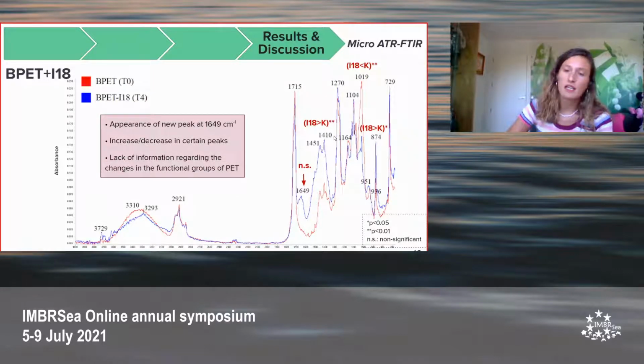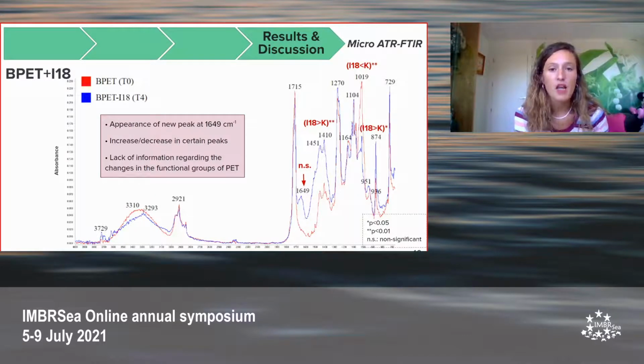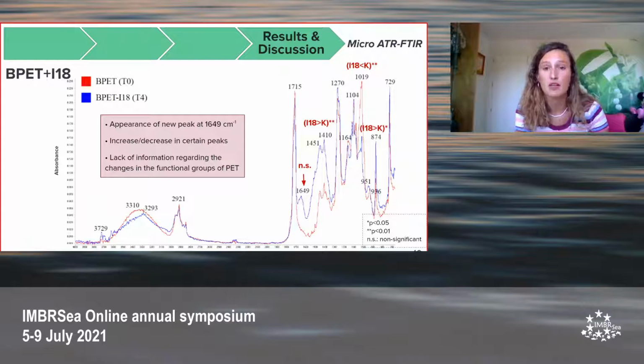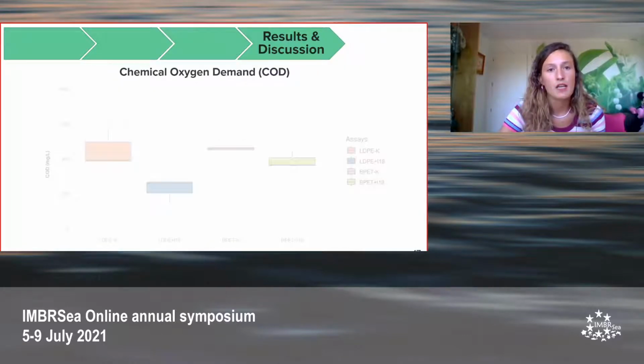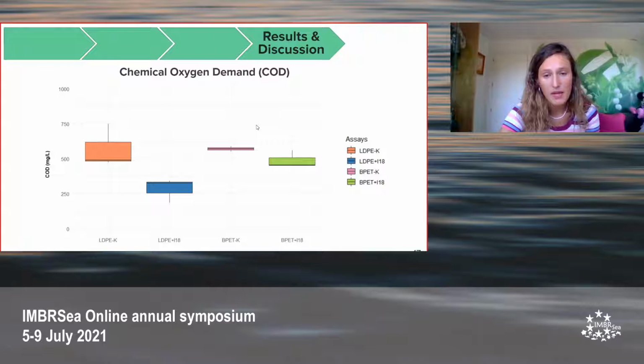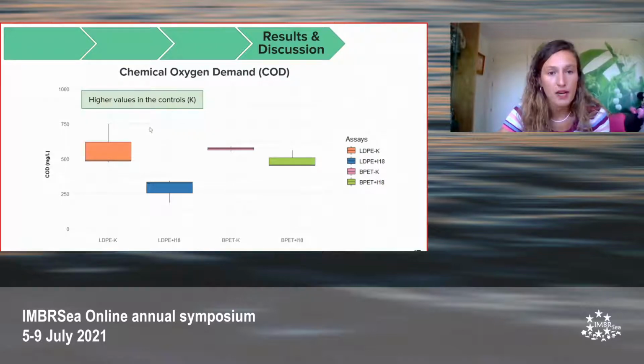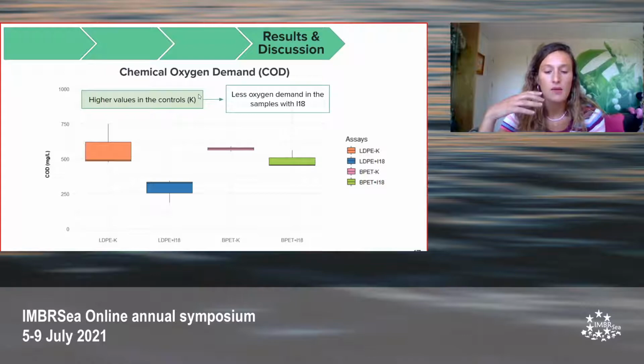These shifts could indicate that the polymer is being degraded. However, there is a lack of information regarding the changes in the functional groups of this polymer. But these results could, in this sense, pave the way for further interpretation of the biodegradation of polyethylene terephthalate. In the case of the results of the chemical oxygen demand, as we were expecting, we obtained higher values in the controls compared to the ones with inocula, and this indicates that these particles with inocula are more degraded, so they need less oxygen to be degraded. This is a biodegradation sign.